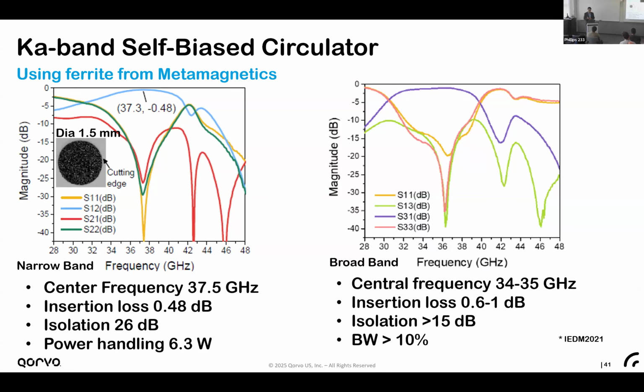First of all, it's possible. It's doable, and you just need a smaller size of the discs. This might be like 0.5 millimeter. So maybe the material itself might resonate or something like that. Material quality has no problem. I think the major challenge is with the process. For example, when you cut the material, how smooth you can make the edge is largely related to your insertion loss. And if you use laser cutting, for example, the heat generated by the laser overburns the material and also increases the loss. So we paid a lot of attention and worked a lot on how to reduce the loss when we incorporate these discs. And have you looked at cryogenic temperatures?